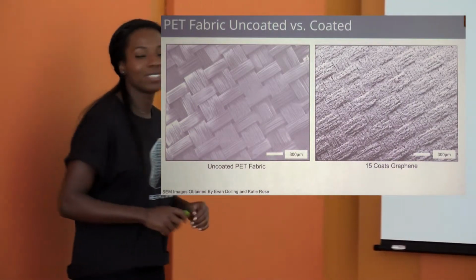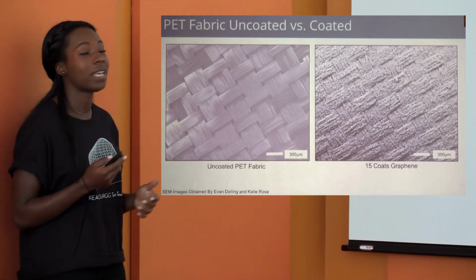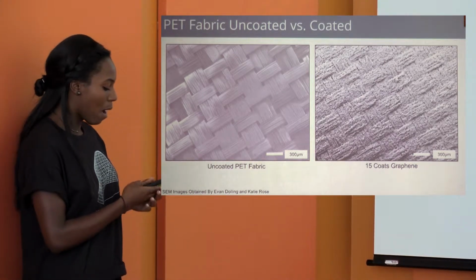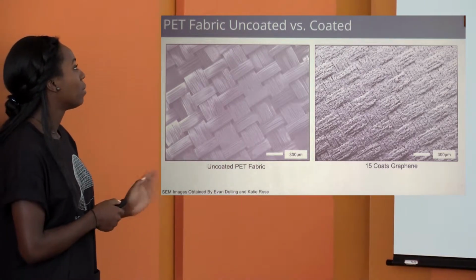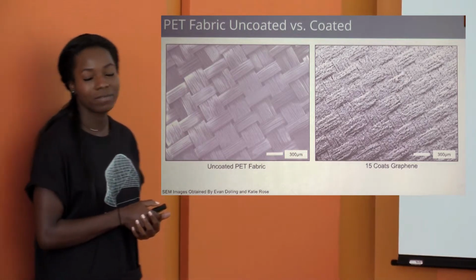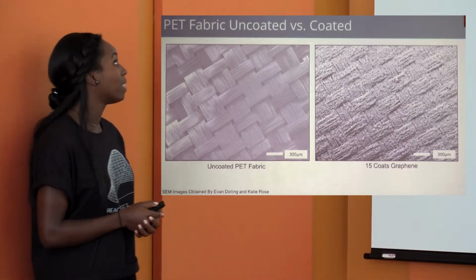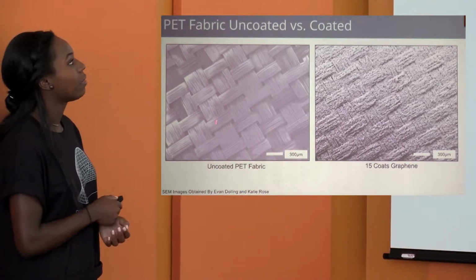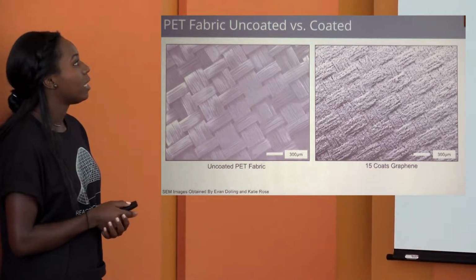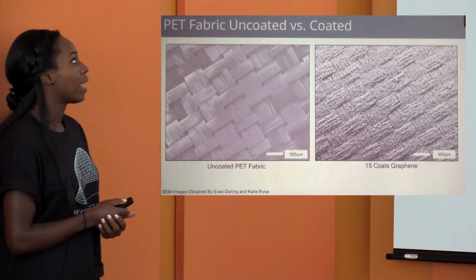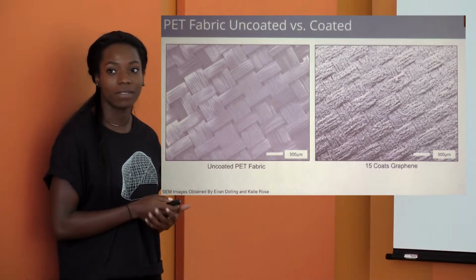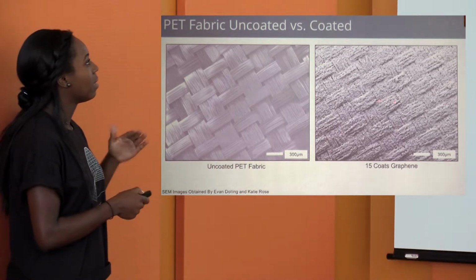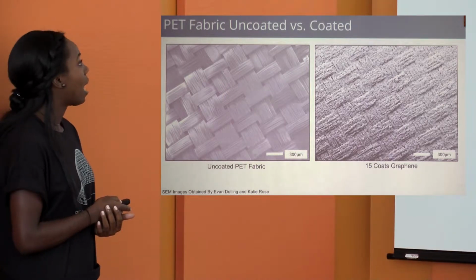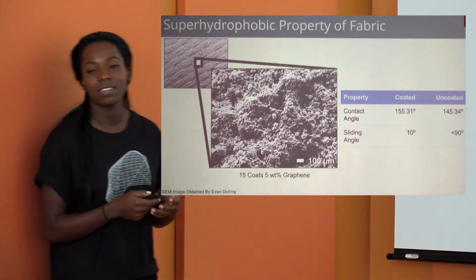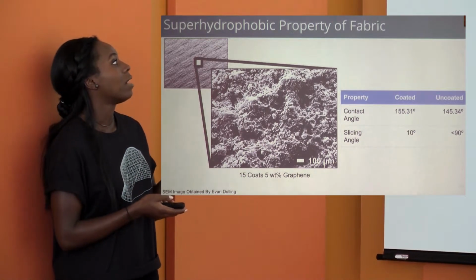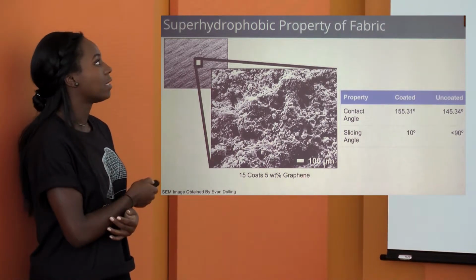Okay, so with the help of some of our graduate student mentors, Evan and Katie, we were able to obtain some SEM images of our samples. On the left, you see an image of the bare fabric, uncoated, and on the right, you see the fabric with 15 coats of the graphene nanoplatelets on top of it. You can clearly see there's a weaving pattern of the threads in the uncoated PET fabric. And when we deposit the nanoplatelets onto the fabric, the patterning of the threads helps to create this microscale roughness. You can clearly see that the hills of the weaving create this microscale roughness. And also, when you take a closer look, because the platelets are flat when they are deposited, they form a random patterning, which helps us create this nanoscale roughness.